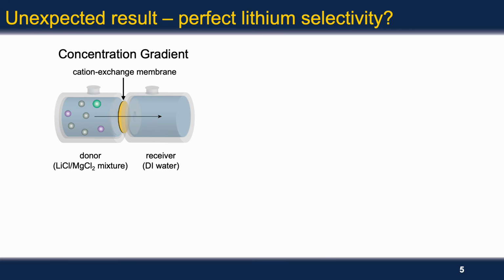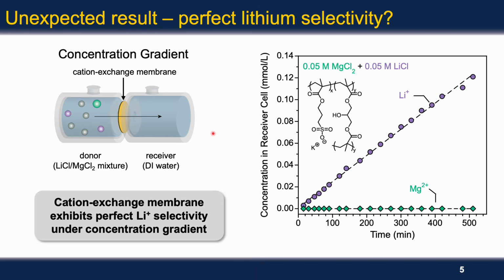In this study, we investigated negatively charged membranes and concentration gradient-driven transport across the membranes as the basis for separation. This study essentially got started from an unexpected result that we observed in the lab when we tested mixed ion transport across a negatively charged membrane in a diffusion cell. In this type of experiment, we found that lithium ions can readily permeate across the membrane, so the concentration in the receiver cell increases versus time, whereas the magnesium concentration was essentially undetectable throughout this experiment.